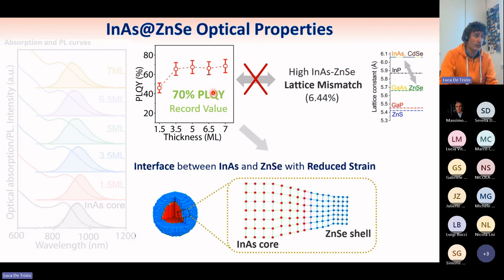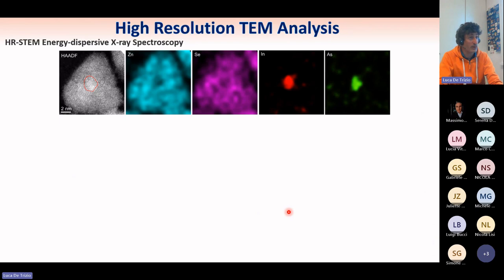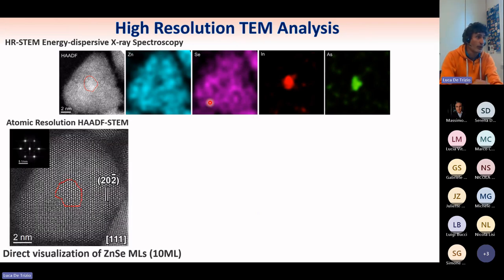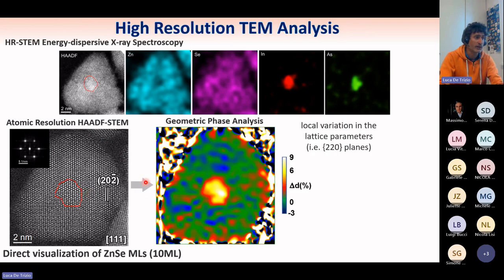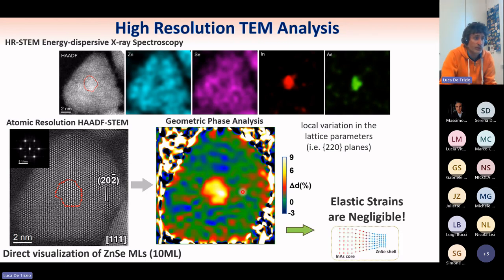And this high quantum yield indicates that there should be something which we can call a magic layer in between the core and the shell, allowing for the stress to be reduced between the two. So we investigated the nature of this layer. We first performed high resolution TEM. Here you can see a single core shell structure in which the core is made of indium arsenide, as you can see from the color code, and the shell is zinc selenide. If we go to higher resolution, here you can even count the atomic columns, and you can count the number of planes here. So you can count the thickness of the shell and the size of the core. And moreover, you can even judge how these lattice parameters vary along one single nanostructure. And here you can see that the core has lattice parameter compatible with indium arsenide, and the shell lattice parameter compatible with zinc selenide, meaning that there is no strain in this structure.